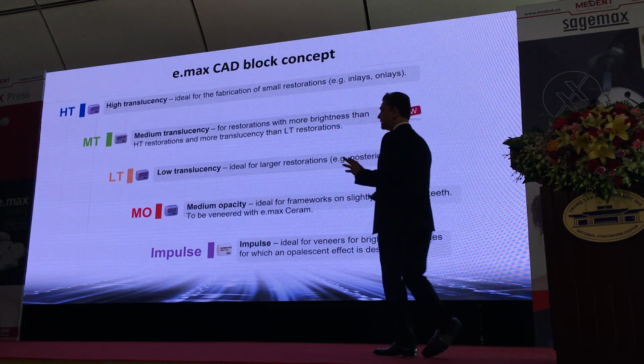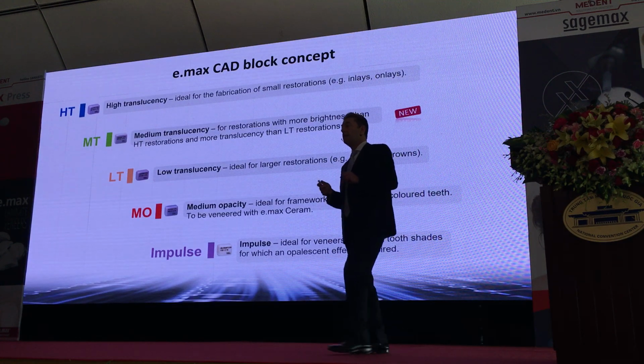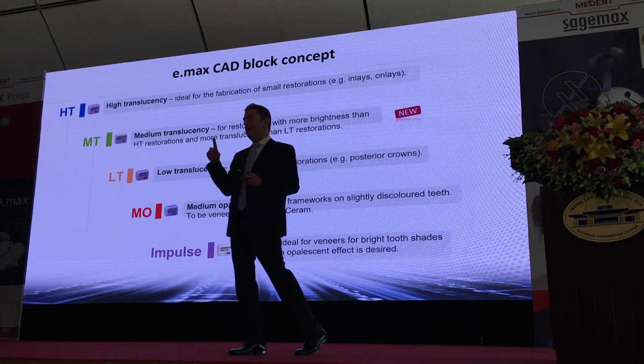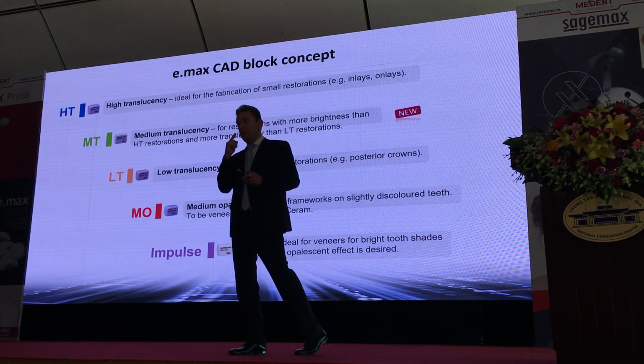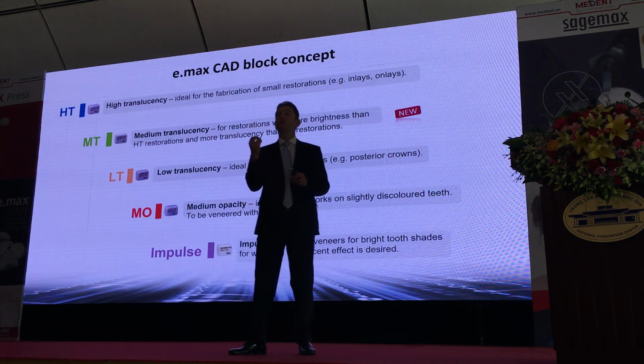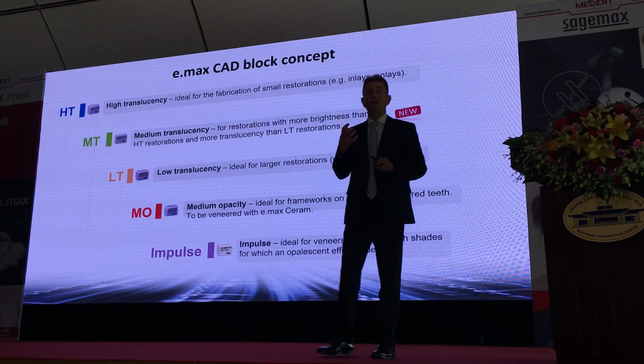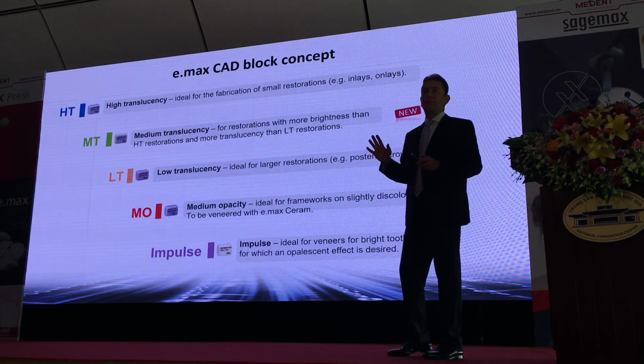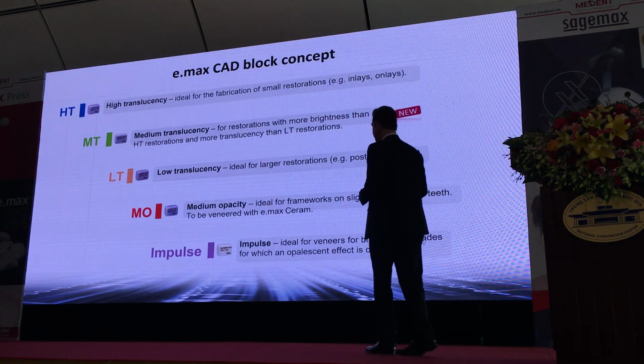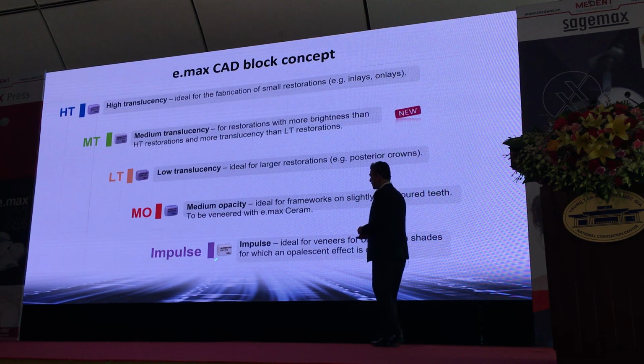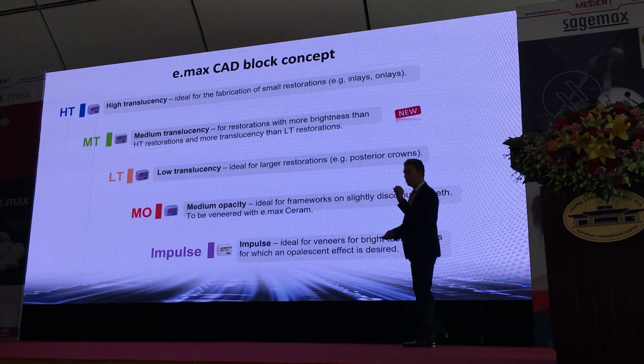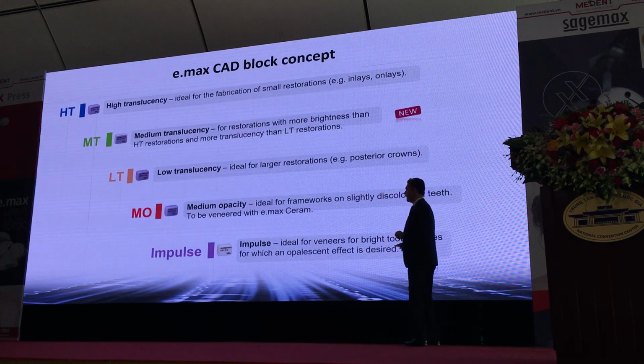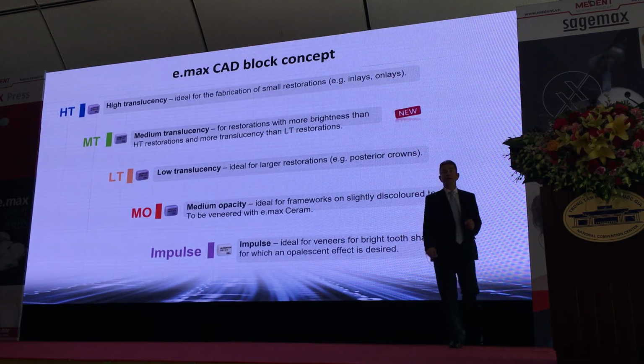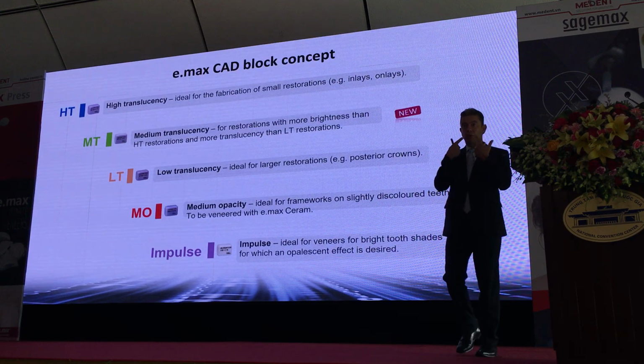So that's very important. And the dental technician has even another ingot for the pressed version, which is called HO, that is very opaque. So sometimes in the anterior, your discoloration is so strong that this needs to be blocked out with a ceramic. You cannot block it out with a cement. This has to be blocked out with a very opaque ceramic. And this is the Impulse ingot, which I've shown you before for this thin veneer. And this one is very opalescent. It's very suitable for younger patients that still have some opalescence on their teeth.